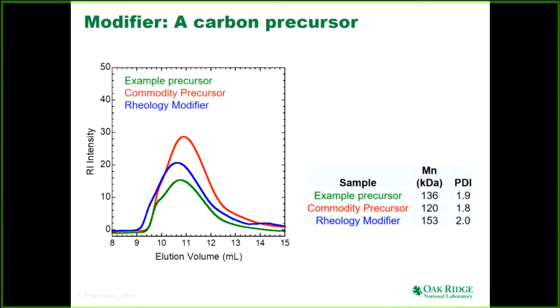Nevertheless, I wanted to mention here that the rheology modifier, marked in blue color, has a significantly higher molecular weight. This is something that we synthesized in our lab. It's also a carbon precursor. It is PAN, polyacrylonitrile, and it has a controlled polydispersity index, slightly higher but more or less okay, 1.8 to 1.9. And we have compared it with commodity precursor as well as some example carbon precursor that exist in our lab. You can see that it is slightly higher in molecular weight, but more or less okay. This is size exclusion chromatography data using a refractive index detector, RI detector, and elution volume. So just wanted to say that this is a type of PAN precursor that we have synthesized, which is nothing but a PAN with certain molecular characteristics.